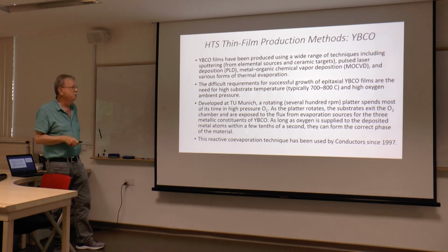And one of the ways, and again, this is 10 years out of date, is they have this spinning platter that spends most of its time under high pressure oxygen. And every once in a while, it goes through the area where you're evaporating the metallic constituents, and then it zooms back into the area where the oxygen is at high pressure, and you can actually grow the material. And thinking about it, you'd say, really, that works? It's like pulsed laser deposition. It didn't seem like it should, but it does. And this is this Conductus company that we showed their filters from.